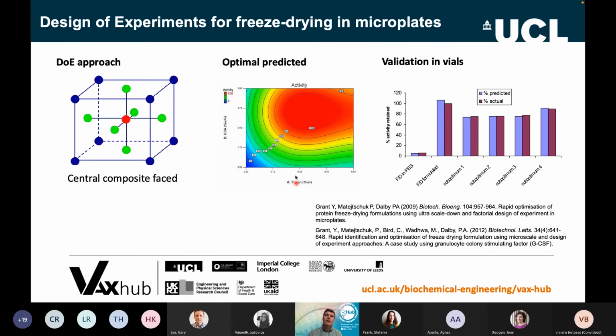And again, in that previous work, we had already shown that we could use design of experiments. We typically used central composite face designs to get an optimal formulation, and we had validated that in vials and shown that the predictions from microtiter plates and the vial performance were in very good agreement, which shows the design of experiments approach works really well using microplates in freeze dryers. So that was the basis, and the plan of action now was to do the formulation work for the ChAdOx platform. So I'll move into what we got.